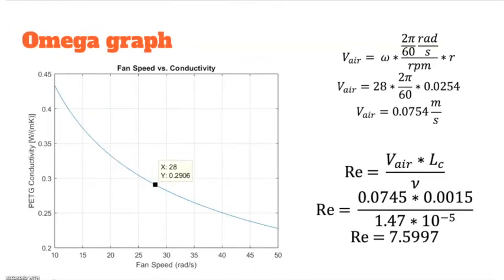Now that we have the experimental value of the convection coefficient, we use it to calculate the value of the thermal conductivity of PETG, and ultimately use that to determine the speed of the fan. We decided to do this by calculating a range of thermal conductivity values using a range of values we thought were reasonable for the speed of the fan. We then plotted both of those values and found which omega related to the known value of thermal conductivity of 0.29 watts per meter Kelvin.